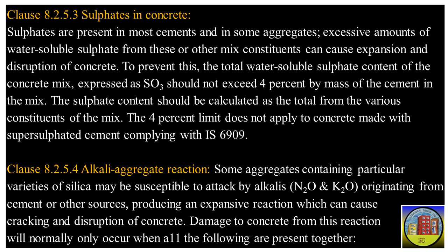Clause 8.2.5.3 Sulfates in concrete. Sulfates are present in most cements and in some aggregates. Excessive amounts of water-soluble sulfate from these or other mix constituents can cause expansion and disruption of concrete. To prevent this, the total water-soluble sulfate content of the concrete mix, expressed as SO3, should not exceed 4% by mass of the cement in the mix. The sulfate content should be calculated as the total from the various constituents of the mix. The 4% limit does not apply to concrete made with supersulfated cement complying with IS 6909.